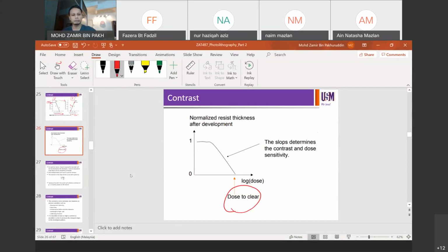Right? So from the focus exposure matrix, the engineer will decide what focus we have to use and what energy we have to use in order to get our desired CD, and then we fix the setup: the focus, the energy, the CD. Then we pass it to production. It goes into the process pack, and then we monitor the fluctuation in the mass production. Right, so you can follow the FEM.